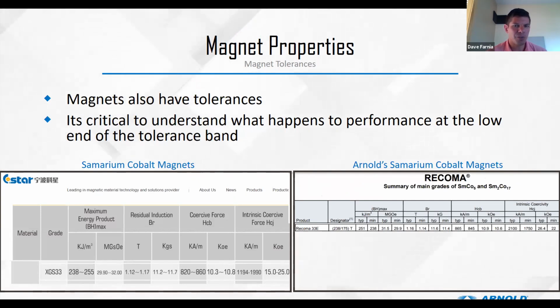We like to use a variety of magnets when we're making rotors. Some of the samarium cobalt magnets that we would get from our Chinese facility, they have very nice properties. But we have to look at those tolerances. If we compare the basic properties for a samarium cobalt that we would get from our Shenzhen facility to a samarium cobalt that we would get from our Swiss facility, we can see that the MGOE, the strength, is about the same. So 29.9 to 31.5, 29.9 to 32 MGOE, or mega Gauss Oersteds. All right, well, very similar performance.